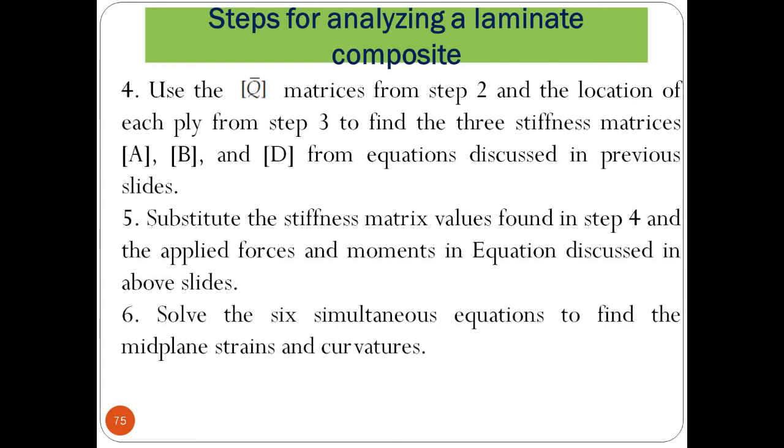Now with the help of the developed forces and moments equations and the different stiffness matrix values, we will have 6 simultaneous equations, and these 6 simultaneous equations are used to find out the 3 curvatures and the 3 corresponding strains.